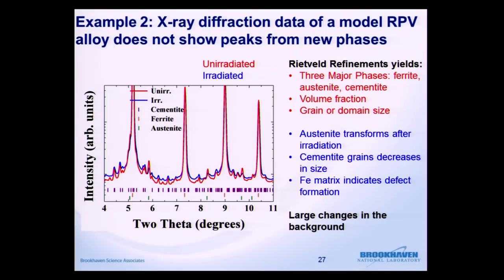We also see quite a large change in the background. These curves have not been offset from each other. This difference in the background is real. What we don't see is our peaks from the nanoprecipitates. So we don't see a fingerprint in these patterns from the nanoprecipitates, and that's really what we were looking for here. These changes in the microstructure are very significant for the aging of the materials, but we really wanted to identify the nanoprecipitates.